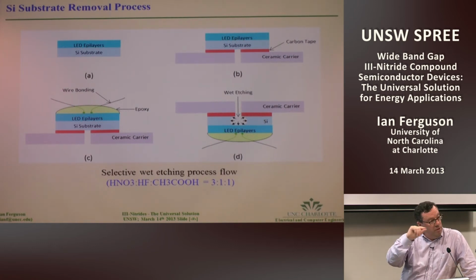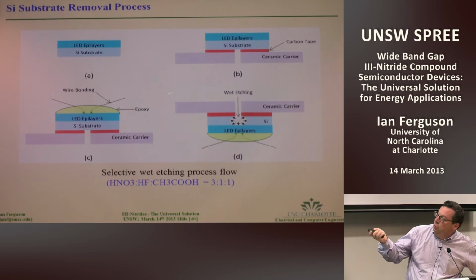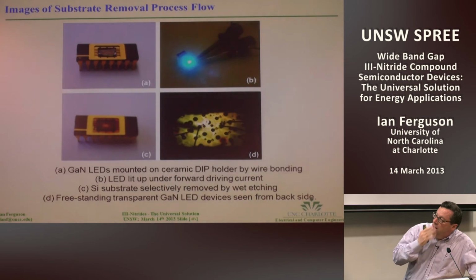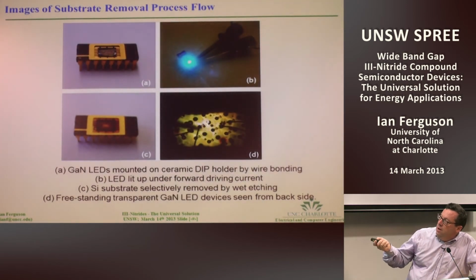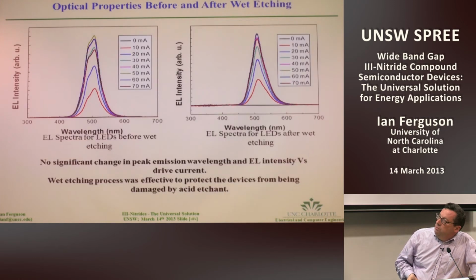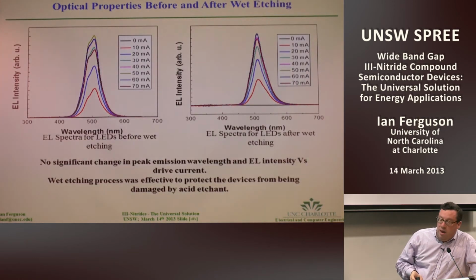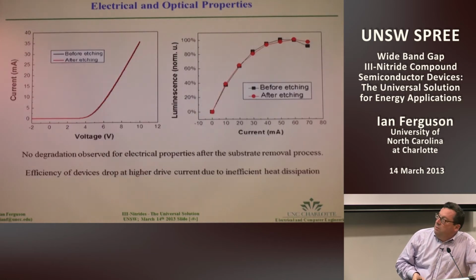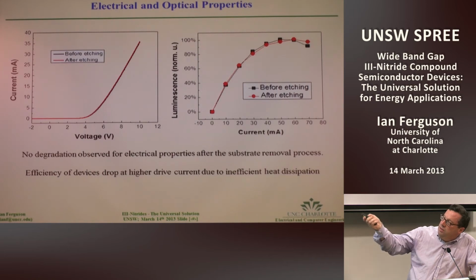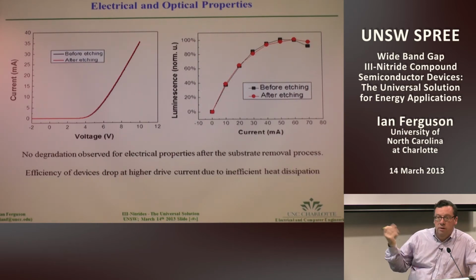So they have a thin layer of gallium nitride, and they've removed the other things that may cause waveguiding. What we were doing here was showing the ability to remove these substrates and just keep these very thin epilayers. This was just on a dual inline package. This is an LED where essentially we've removed the substrate from the device. PL, or electroluminescence, stayed the same, and the behavior of the device before and after was the same. These weren't on heat sinks, so you get rollover from heating of these devices.